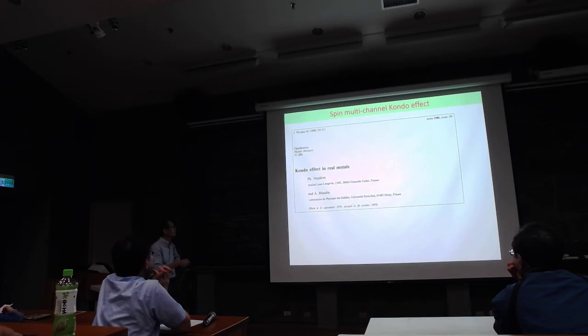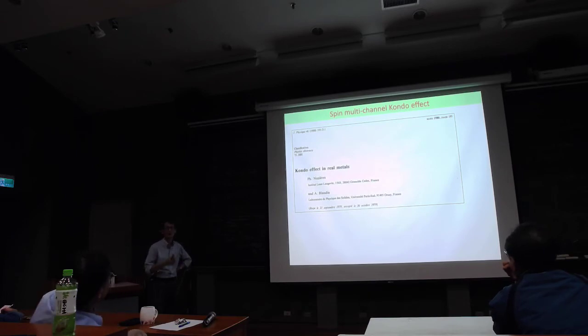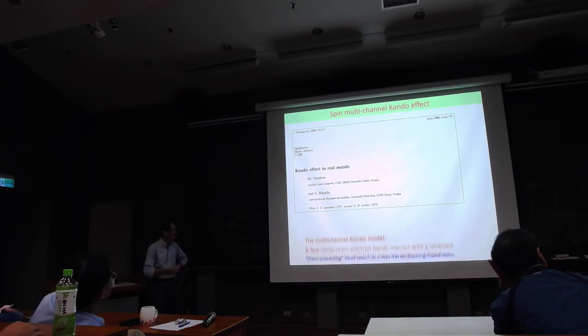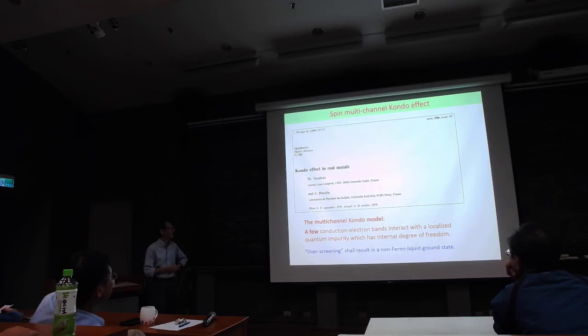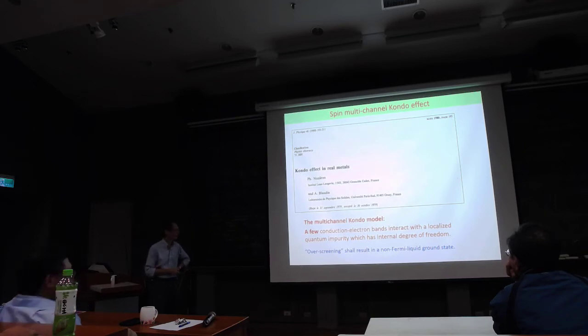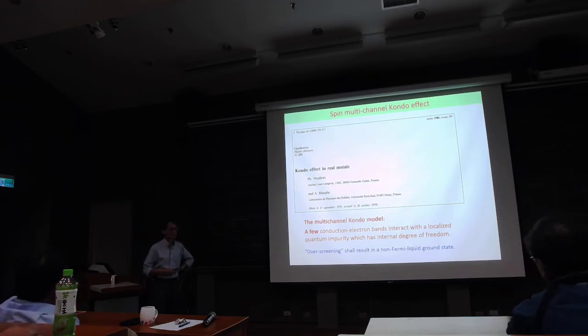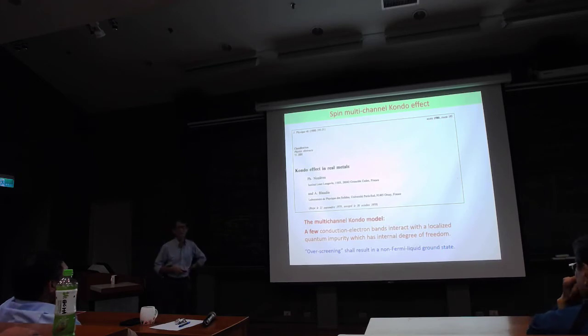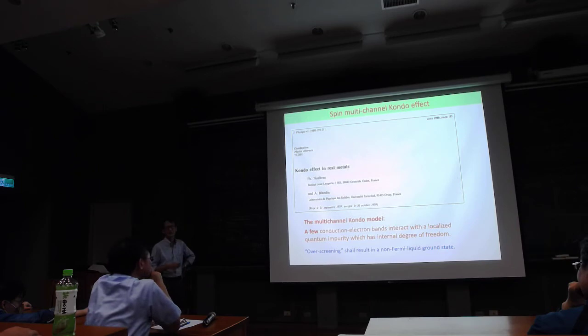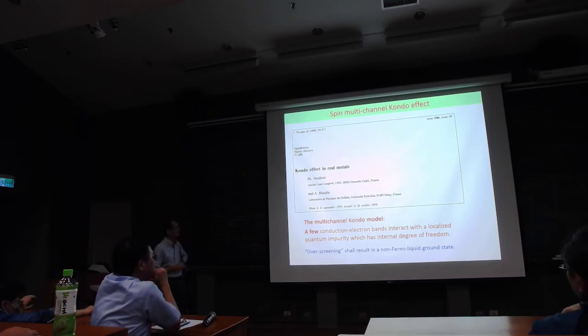And then four years later, in the 1980s, a very famous French group came to the idea that in the original Kondo spin problem, you don't need to be constrained to one Fermi sea. They considered that if you have more channels, so-called channels of Fermi sea, these channels will compete to screen the spin of this magnetic impurity. So there will be an overscreening of the moment. And if there's overscreening, can we still have a stable Fermi liquid state, or can we no longer have a Fermi liquid, and then there will be some kind of so-called non-Fermi liquid behavior. So they already got this idea in